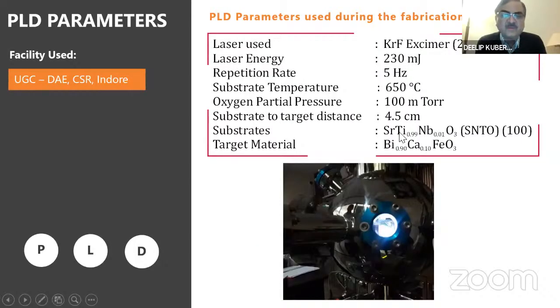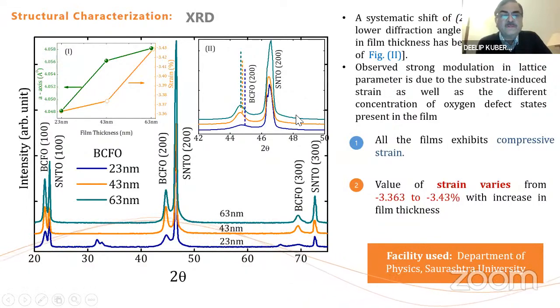This is the niobium doped STO. This is an N-type substrate, because my material is a P-type material. So basically we are growing a PN junction diode in the form of thin films, that is P-type material deposited on the N-type substrate, which is an oriented 100, single-side polished substrate. So therefore, these are the powder diffraction peaks actually, and